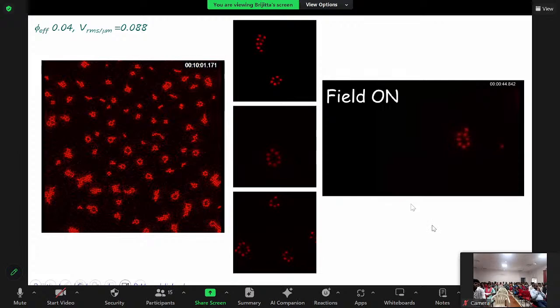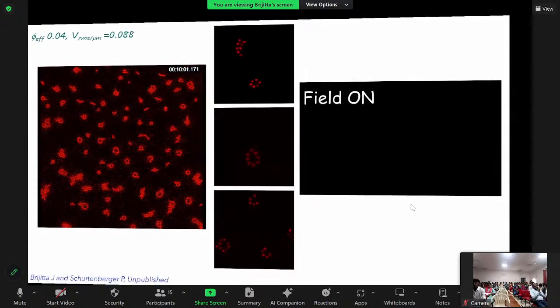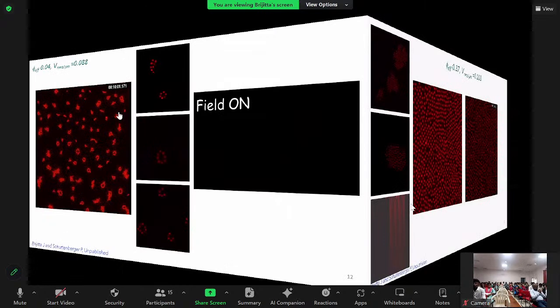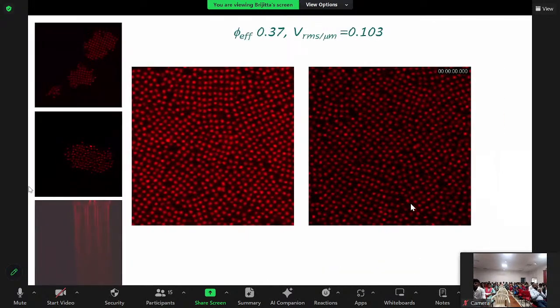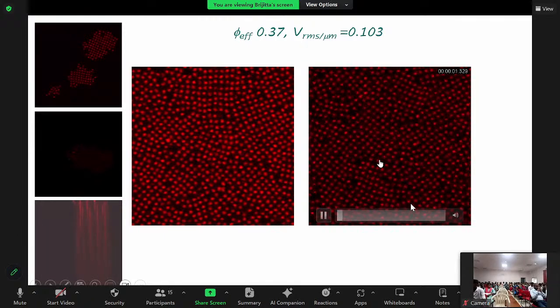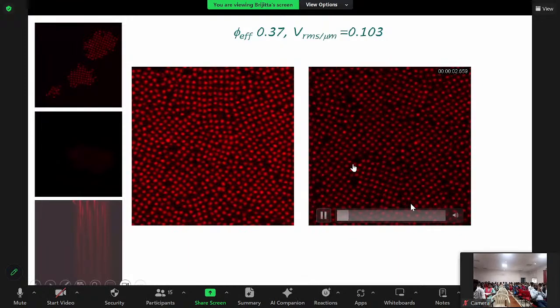So they also have shape memory, and it is good that such materials can be used for self-healing, where once they lose their structure, they can recover it upon removing the stress which caused the structure change. In other systems, we see the conventional things, like they end up with a body-centered cubic structure, and here you can see long strings in the Z direction, and this is the large-scale 2D imaging of how these particles behave in a field.